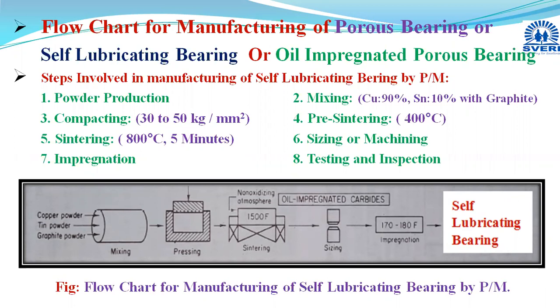After that, the final stage is testing and inspection. Whichever product we have manufactured, we check whether it is correct in shape and size, in all dimensions, and whether it has any defect or is defect free. We also check its properties like microstructure, composition, tensile strength, compression strength, hardness, and porosity. If we find that the product is defect free and provides the optimum properties we require for practical use, then it is certified, marked as okay for practical use.